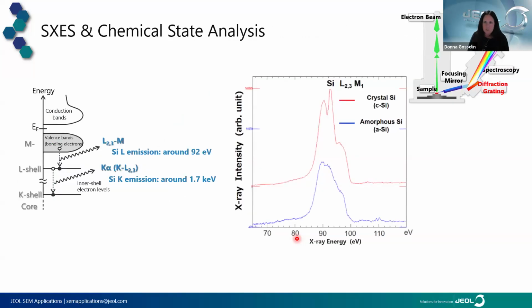As I mentioned before, because of this very high energy resolution and high peak to background levels, we get very high resolving power that allows spectral acquisition, even in the valence band, to be observed. And this is where we get insight into chemical state differences between compounds or crystalline versus amorphous materials. So here I'm showing an example of crystalline silicon versus a spectrum of amorphous silicon. So peak position and peak shape changes help us get an understanding of amorphous versus crystalline material, or some kind of combination of the two.